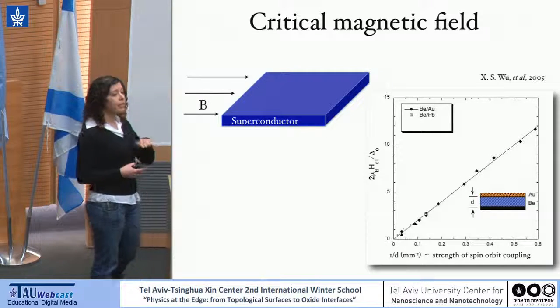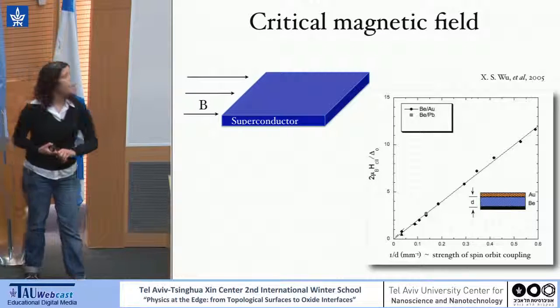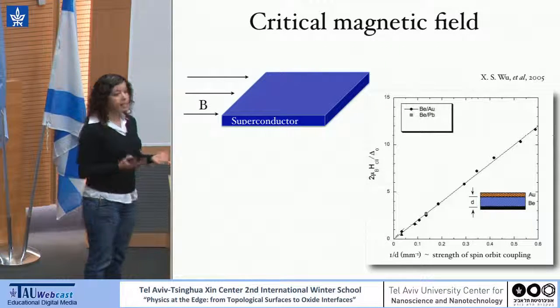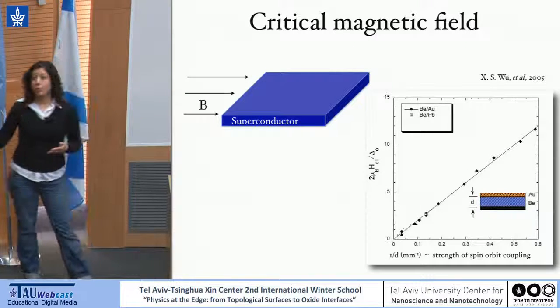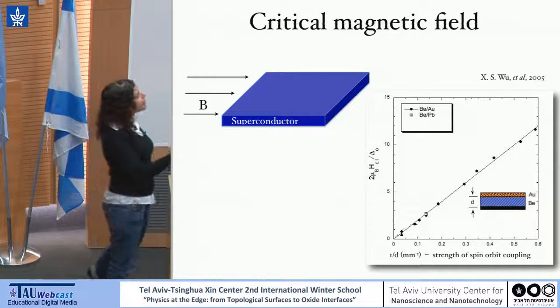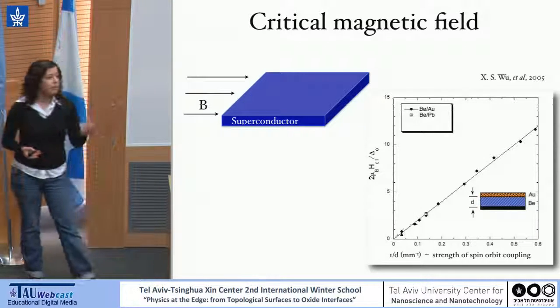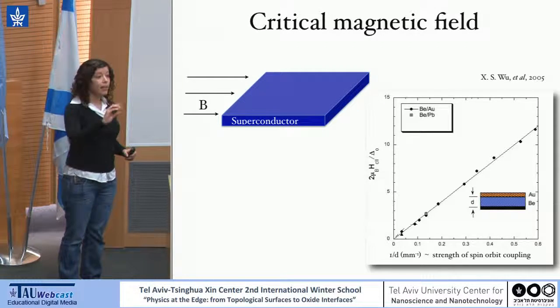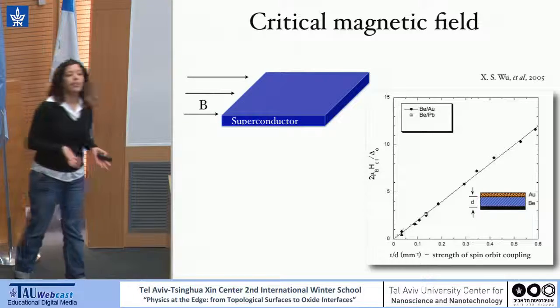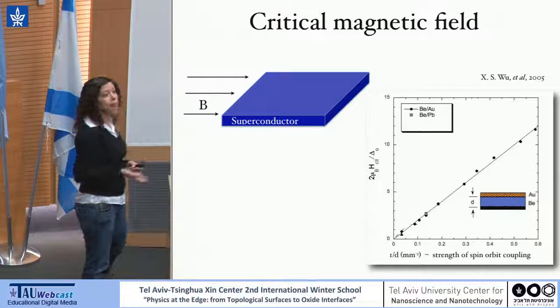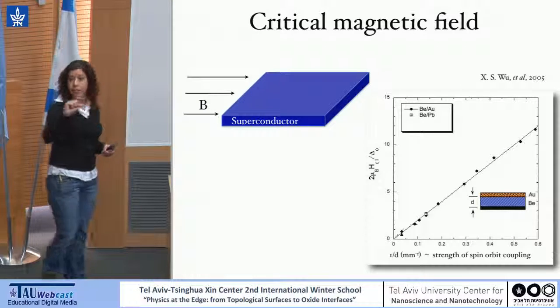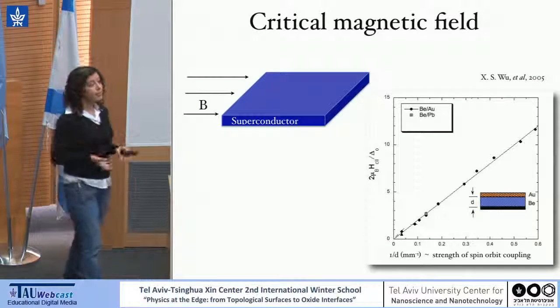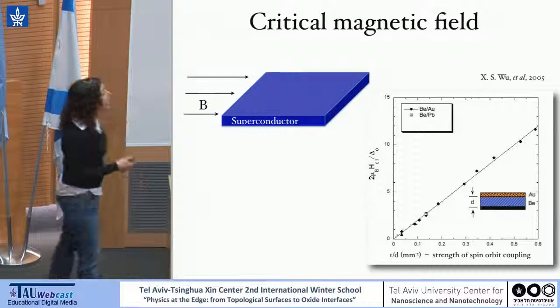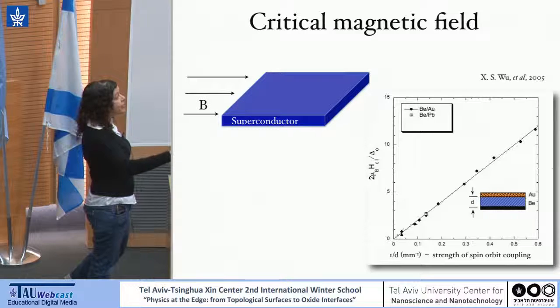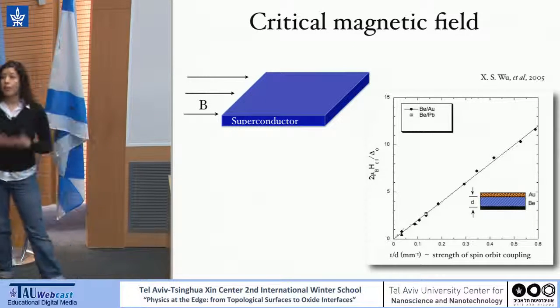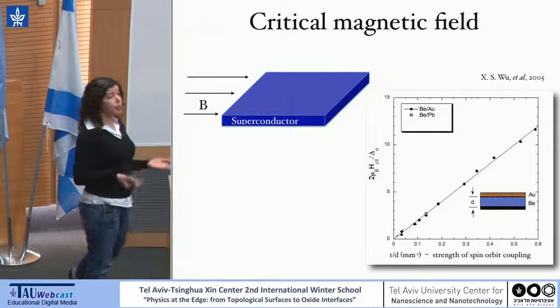And one of the things, as we also heard in the previous talk, that happens when we have superconductivity and we apply parallel magnetic field, which means just a Zeeman magnetic field in the system, is that the critical field, the critical Zeeman field, changes as a function of the spin-orbit coupling. And here it is shown in a nice experiment. Basically, they were taking thin films of beryllium, depositing gold particles on top of them to induce spin-orbit coupling in the system, and measuring the critical parallel field as a function of the thickness of the film. The thinner the film, the stronger the induced spin-orbit coupling of this system. And what they observe is basically that the critical field grows linearly as a function of 1 over the thickness, or as a function of the strength of the spin-orbit coupling.